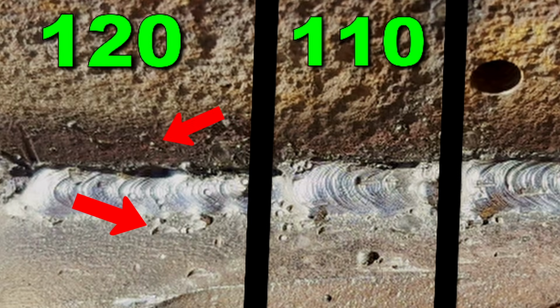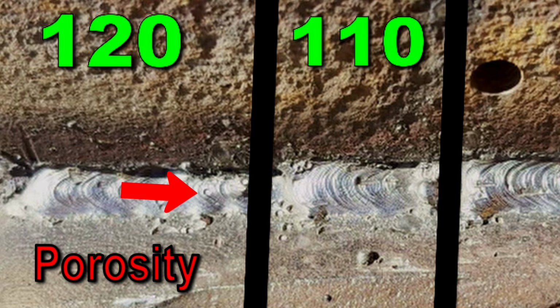We also have some spatter here, which is typical when welding on rusty, dirty metal. Those imperfections vaporize into gas bubbles and pop and spit out molten metal. This is even more common underwater, where the arc is constantly fighting to maintain a gas bubble against the pressure of the water. We also have some porosity here. Porosity is those tiny pinholes on the surface. It's basically trapped gas bubbles caused by contaminants like rust that didn't have time to escape before the weld froze solid.